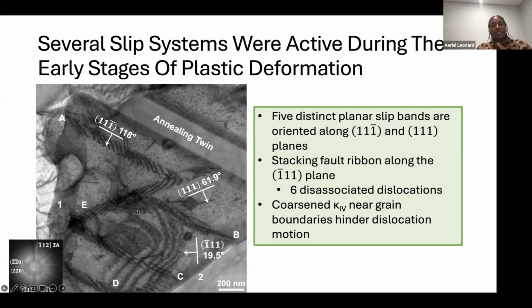Regardless, you can see that the deformation is really constricted within the grain. You don't see a lot of transfer from grain to grain in the material, but we see some very interesting things that serve as a precursor to what we should be looking for as we continue to go on.